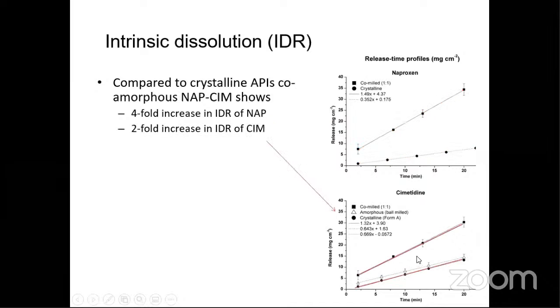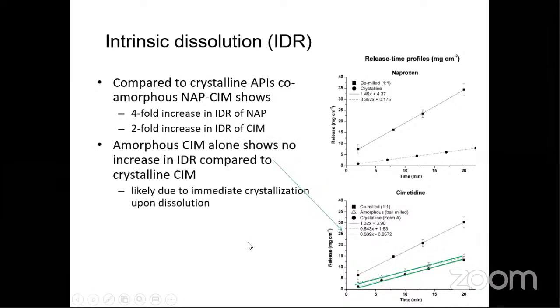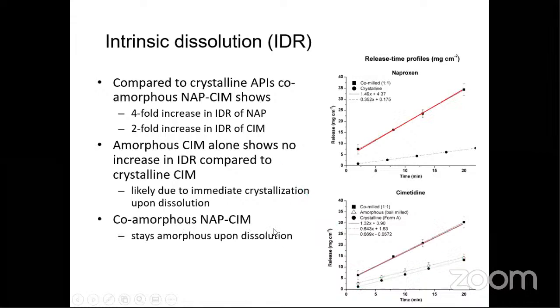Also for cimetidine, the crystalline form dissolves very slowly, and the coamorphous one is much faster. The pure amorphous one is a little higher but not as high as the coamorphous one. This is because of immediate crystallization upon dissolution - once dissolution starts, the amorphous cimetidine recrystallizes very fast, decreasing the dissolution rate.